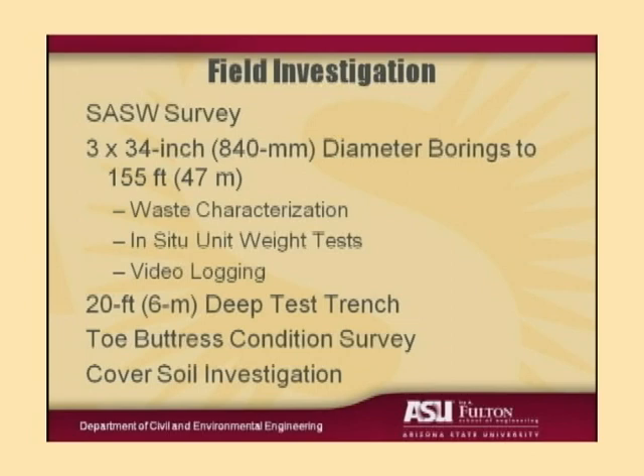And we did detailed waste characterization of the waste recovered in the bucket augers. We conducted in-situ unit weight tests on the way down, and we did some video logging of the holes to get an idea of the structure of the waste. We also did a large test trench at the surface of the landfill, 20 feet deep, 20 feet wide, to categorize the structure of the waste, and then we also backfilled it with gravel to get an idea of the unit weight. We weighed the waste that we took out, we backfilled it with a calibrated gravel, like a big sand cone test, and used that as an estimate of the unit weight. We conducted a condition survey of the toe buttress and a very detailed investigation of the shear strength of that cover soil on the north slope.